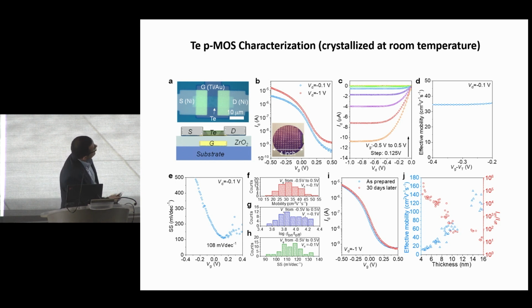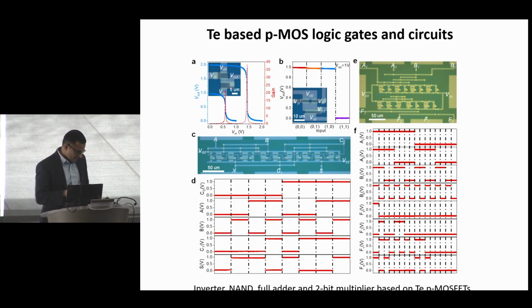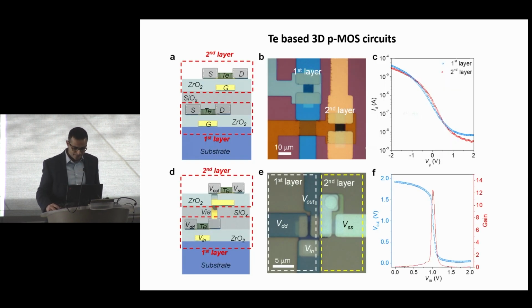Now, the other key feature is there is no mobility degradation at high fields. The mobility is constant. And again, that's because it's a layered structure, so you don't have any atomic scale roughness. Using this approach is pretty scalable. We can do wafer scale processing. So my student Chun-Sung built inverters, NAND, full adders, and 2-bit multipliers on a wafer scale, on a wafer, using this simple process. The yield, of course, is quite high.